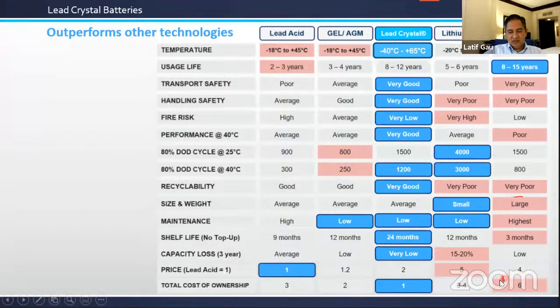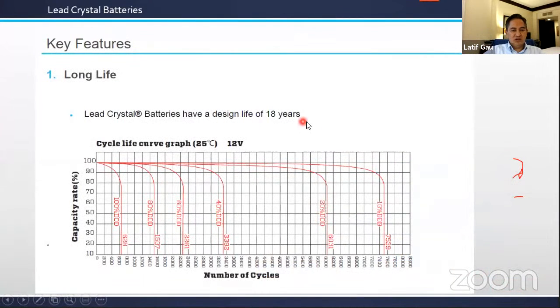Nickel is 4 times. So if you talk about the total cost of ownership compared to the lifetime, toxicity, transport, storage, and everything, we come up with the conclusion that this battery is the best in total cost of ownership. So if you see the key features, the long lifetime can go up to 18 years, because if you see the cycle curve, 25 degrees, 12 volts, you can have a number of cycles. If you have only DOD, depth of discharge, to only 10%, it really can go up to 18 years, 20 years.